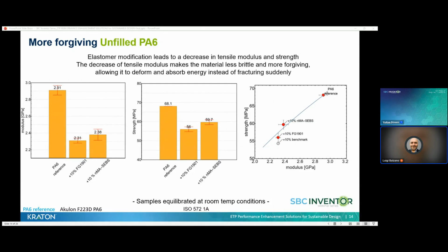So what I was saying is that the decrease of properties is almost the same for both modifiers, indicating that when it comes to tensile properties of unfilled polyamide 6, the changes in the molecular structure of the novel malleated SEBS have a little influence. This relates to the local deformation processes that are active in the material during tensile loading.